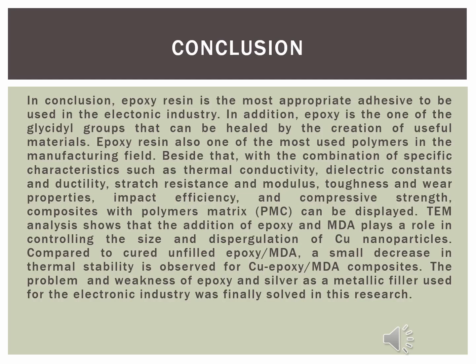Analysis shows that the addition of epoxy and MDA plays a role in controlling the size and dispersion of Cu nanoparticles. Compared to cured unfilled epoxy or MDA, a small decrease in thermal stability is observed for the Cu epoxy or MDA composite. Lastly, the problem and weakness of epoxy and silver as a metallic filler used for the electronic industry was finally solved in this research.